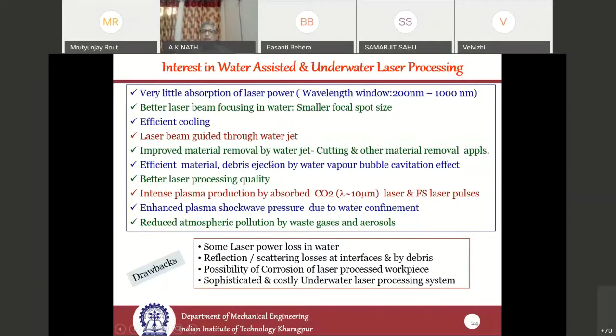Improved material removal by water jet because of high shearing force compared to gas jet, and it is used for cutting and other material removal processes. Efficient material debris ejection by water vapor bubble cavitation effect. Better laser processing quality because of the effective removal of debris. Intense plasma is produced when we are using CO2 laser, and this has also been exploited in many applications. And enhanced plasma shockwave pressure due to water confinement.